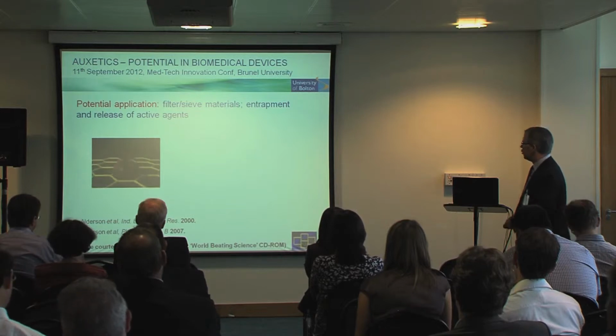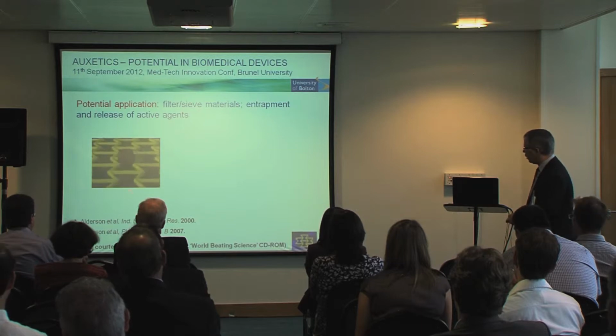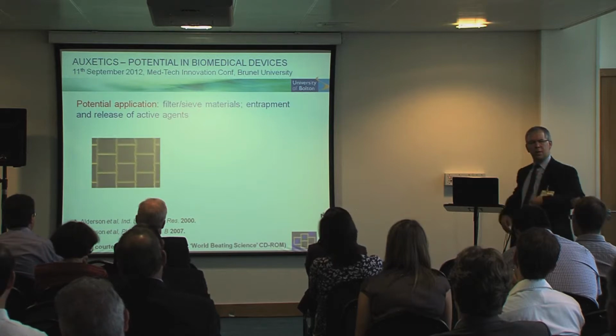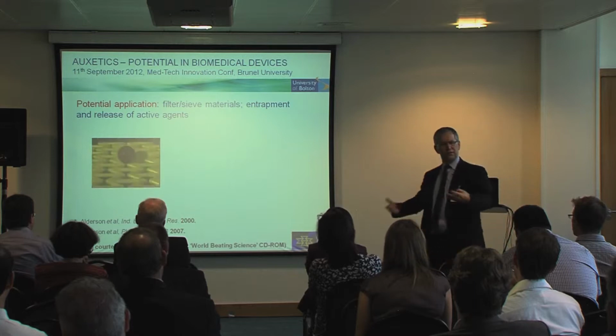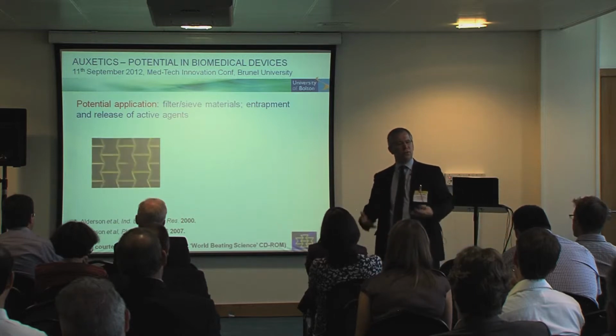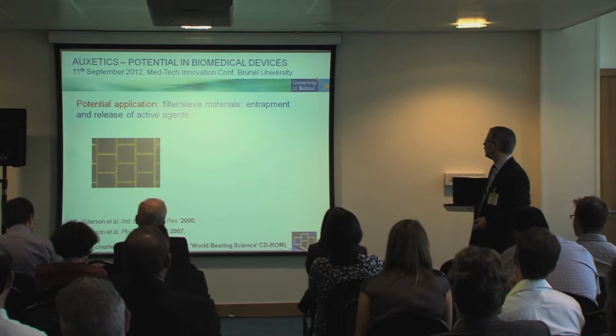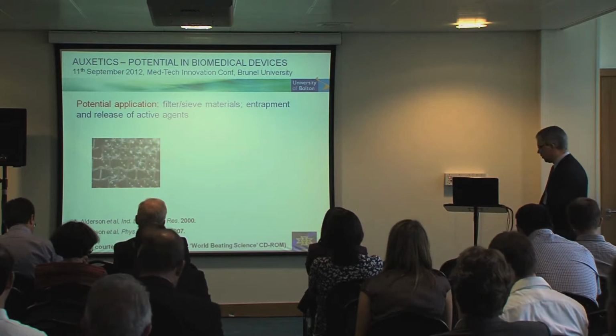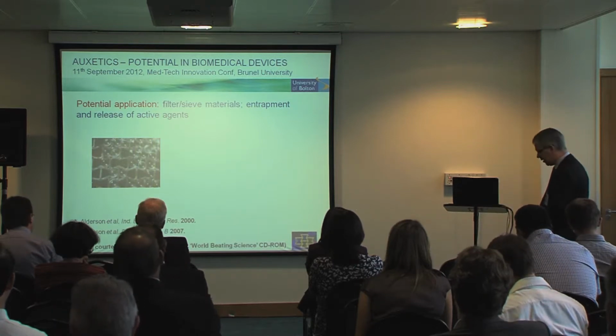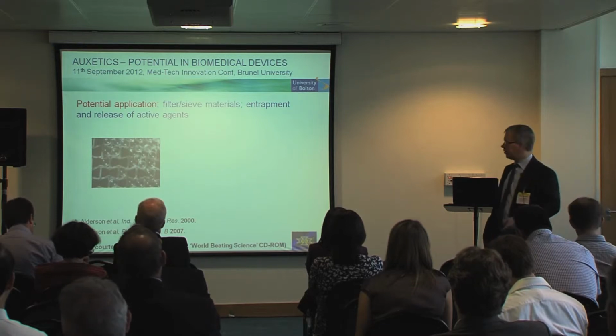If, on the other hand, in a moment we go to the auxetic case, now when you pull, the pores open up in all directions, that particle goes through, so you can either clean the filter or you can release the active ingredient or whatever it might be that you're trying to get to go through that membrane. Okay, and we showed that in a very simple set of tests there, and we've done that in foams and also in simulations of molecular devices.